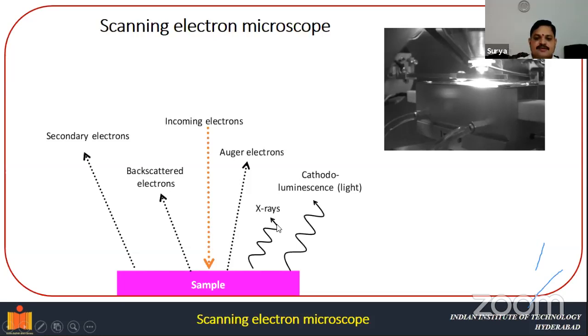So from the X-rays, you can actually know the composition of the material. That's why it's called energy dispersive X-ray spectroscopy, EDAX. Basically, if you want to characterize your material, you have to know the morphology of the material. The morphology can be obtained from the secondary electrons. The phases that exist in your material can be obtained from the backscattered electrons, and the composition of the material you can obtain from the X-rays that we receive from the sample. These are the three important extracts that we can obtain from the sample as soon as we impinge the electrons on top of the sample. From these extracts, you can analyze your materials in a better way. You can say whether your material is single phase or multi-phase, or whether you have achieved the composition that you want or not. Such kind of information you can obtain from these extracts.